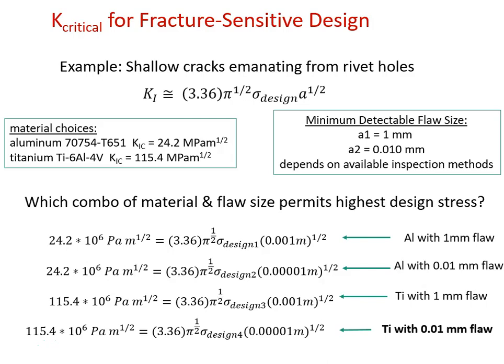Let's assume that we have two different processes to make our part, whatever it is. One process is not very good quality control, and we end up having a minimum detectable flaw size of 1 millimeter. Or maybe we have the same quality, but we have different non-destructive evaluation methods. So in the first case, we can only detect flaws that are 1 millimeter or larger, so we have to assume we have a flaw of 1 millimeter. In another case, either we have better processing, so we don't have as large flaws in the material, or we have better flaw detection.